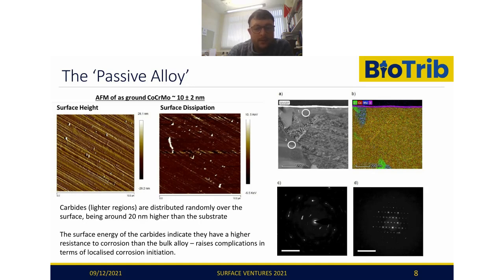Essentially what we see is that with these cobalt chromes, because their crystal structure is metastable in nature, at the very top interface we have this nanocrystalline layer, which is usually an HCP type structure, which arises as a result of a grinding process here, or the shear induced process that's taken place. But then we normally have a fairly well homogenized distribution of elements and grain structure underneath.